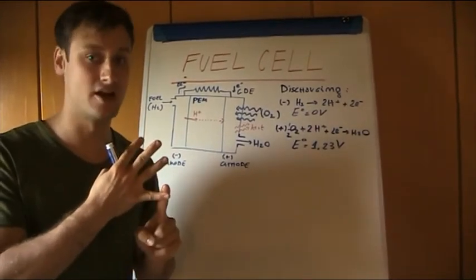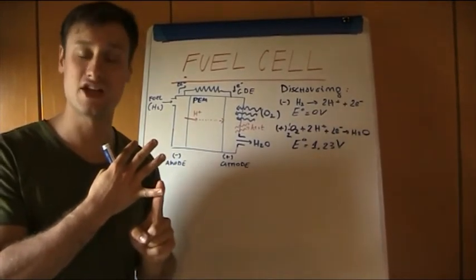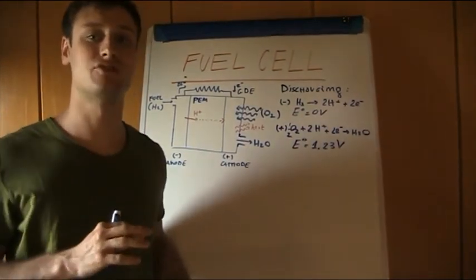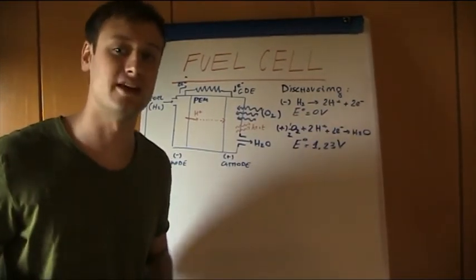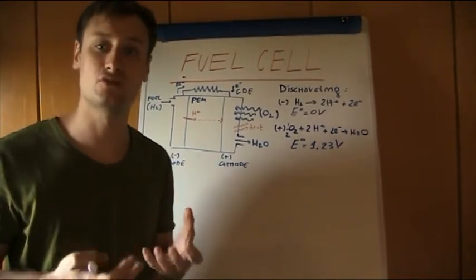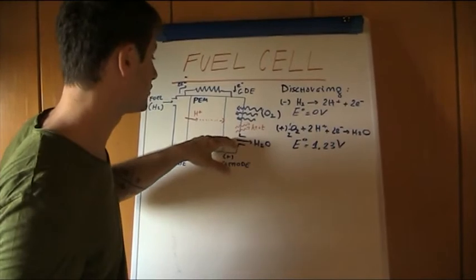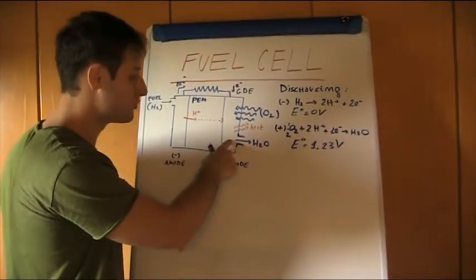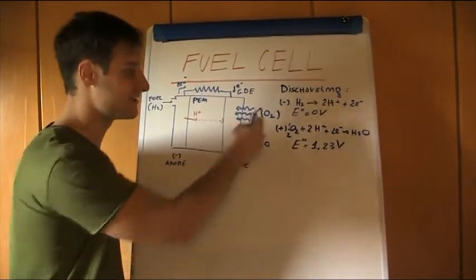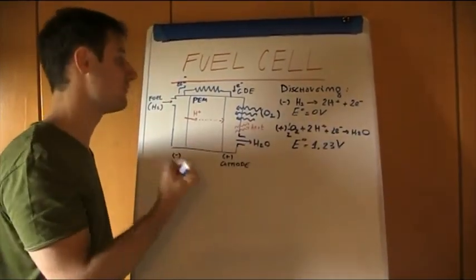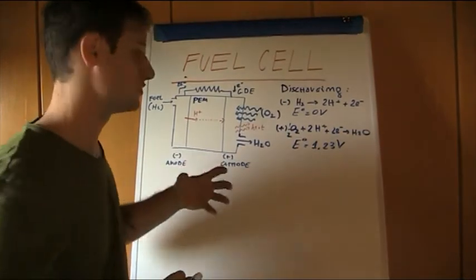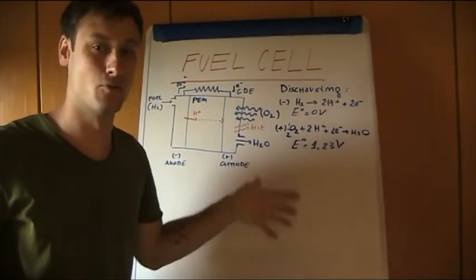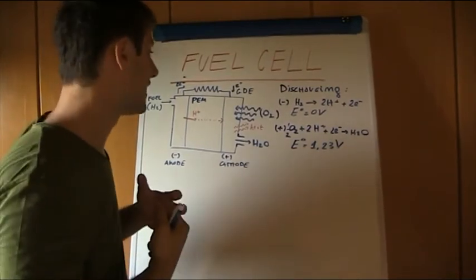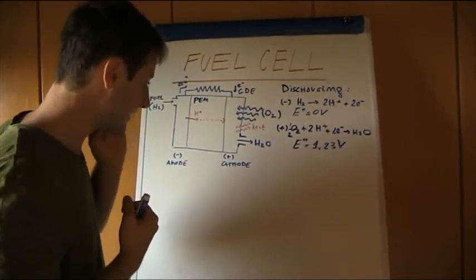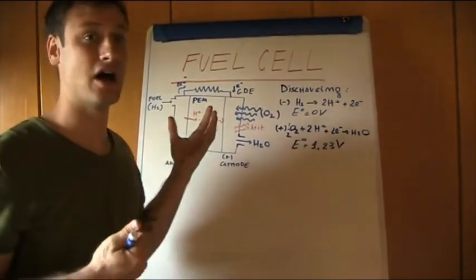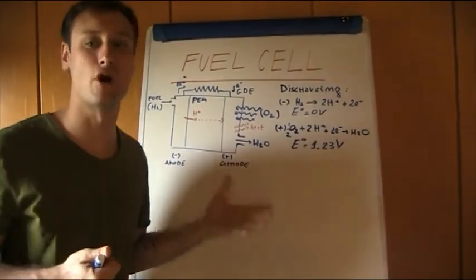We have the Nafion inside in order to allow the passage of H+, and we even have some traces of Teflon, polytetrafluoroethylene. Why? It's simple, because we need to improve the hydrophobicity. We want to allow the spontaneous removal of water when it is created as a product of the reaction, in order to avoid the electrode being completely swollen with water. So we want to avoid filling the electrode with water. The flooding of the electrode should be avoided.